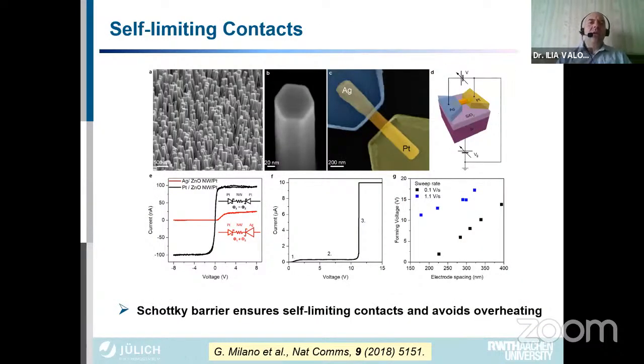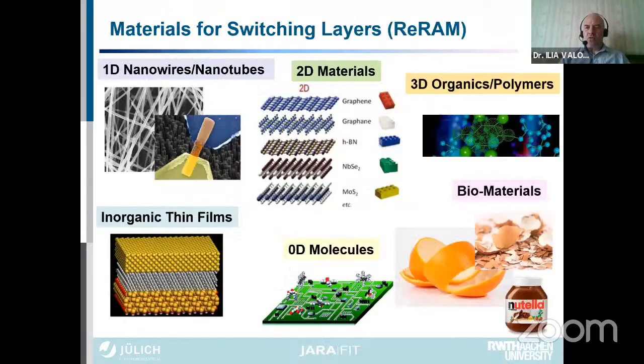Another way to control the reaction is selecting the type of contact, Schottky. The discussion up to now applied to ohmic contacts, but many metals form a Schottky type of barrier with the oxide. In this case, this is another degree of freedom to decide which material to take, as it can limit the electrons that can penetrate into the material, and this way also change the device performance. Now, I spent too much time on the electrodes, and the time is a bit limited to 30 minutes.